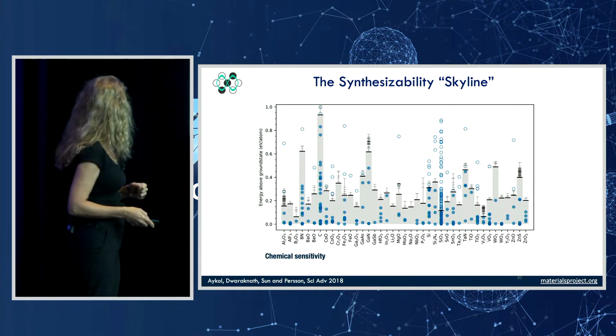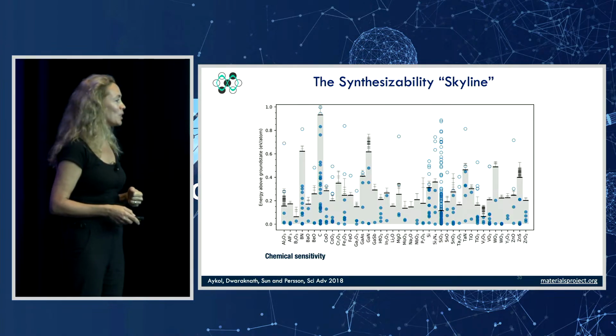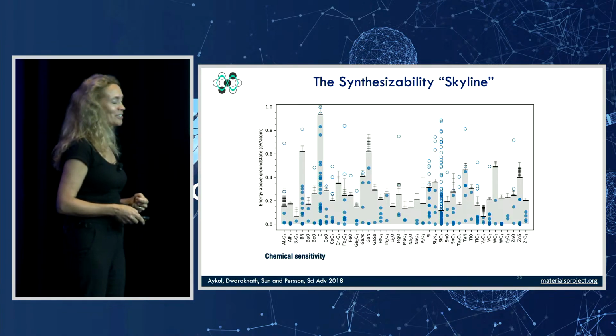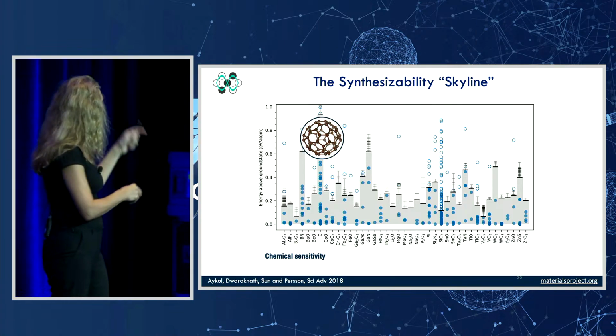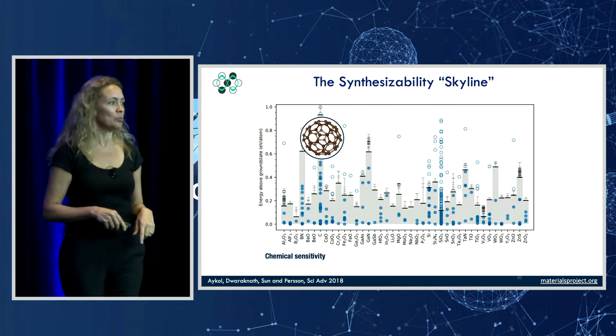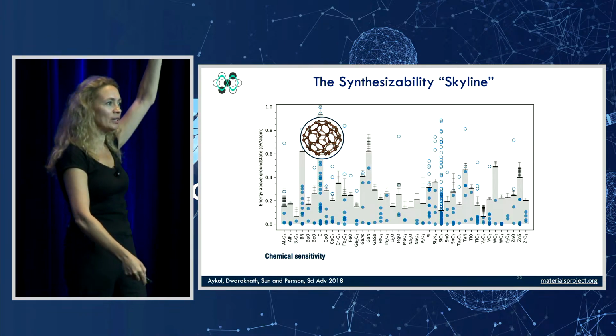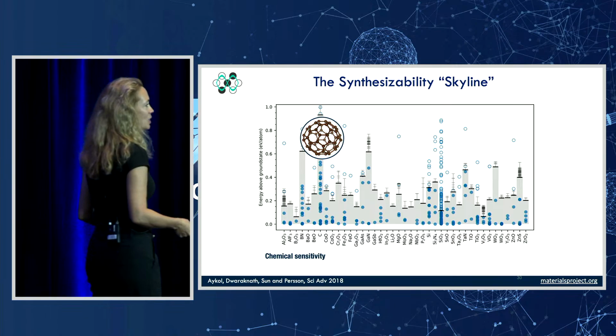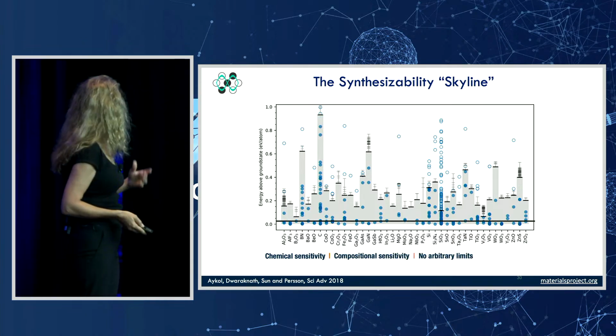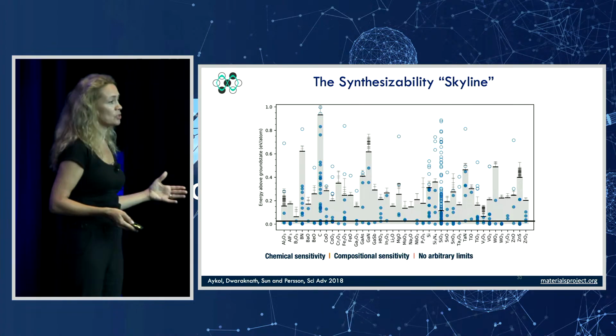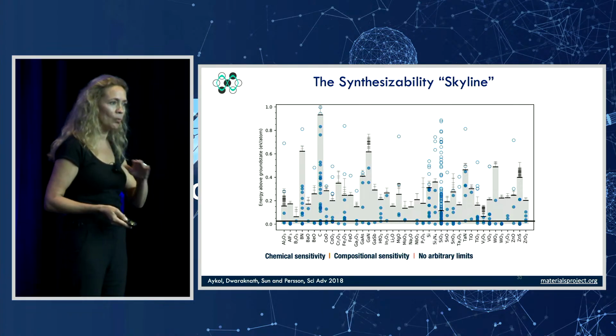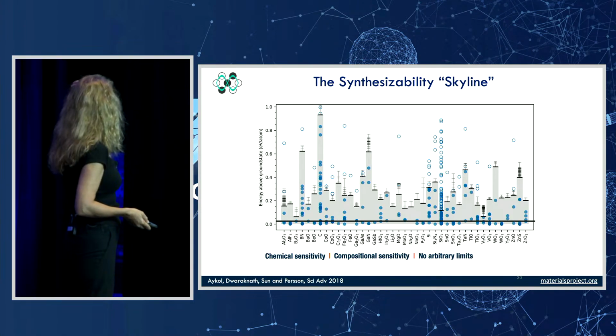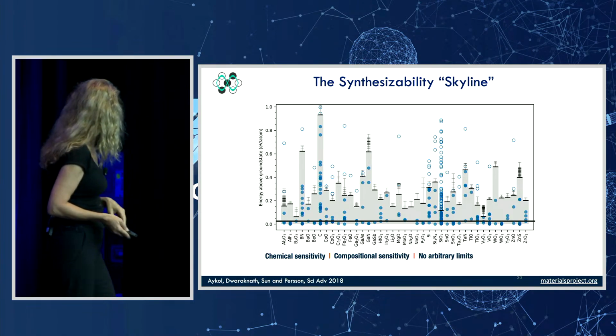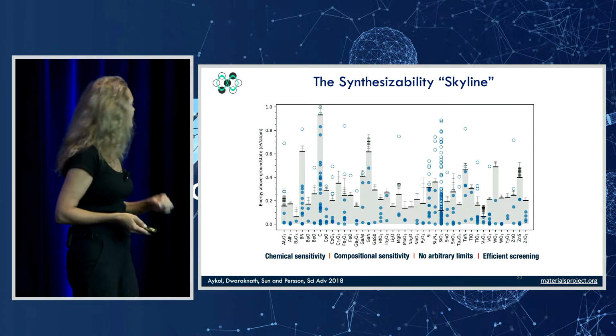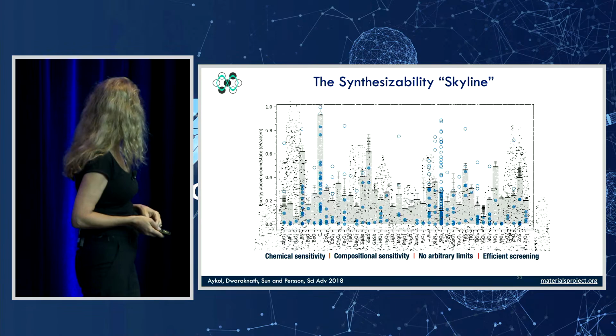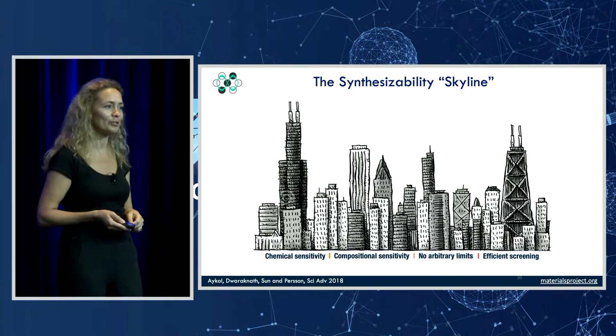So now, of course, you know what the skyscraper is. There's a reason we have Nobel Prizes in carbon, graphene and the buckyball, right? Because we have this enormous enthalpy of formation of the amorphous state, which gives us this wide window of possible metastable carbon structures. So this is a handle for us to understand where are the opportunities and which materials we shouldn't even try to make because they are way outside of the synthesizability limit. So this is another tool in our toolbox in order to guide synthesis, but it's still not enough because it's still just thermodynamics. We do call it the synthesizability skyline because the first author on the paper came from Chicago.